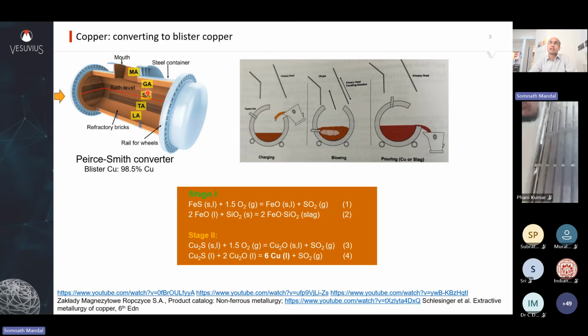Almost 80 to 90% of conversion happens in Peirce-Smith converters, a very common one. Ladles of matte are loaded into this, and then oxygen is blown in. Your iron sulfide oxidizes to FeO, which then reacts with flux and forms the fayalitic slag. Once the matte is oxidized to a level where the iron sulfide is very low, the copper sulfide oxidation starts. This is the second stage, where you convert the copper sulfide to metallic copper.